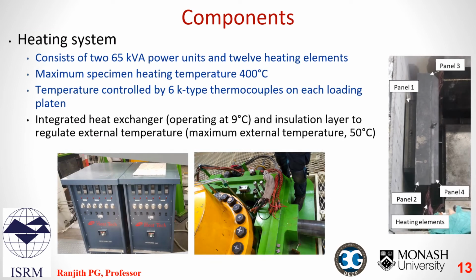The high power heating system is another unique component of this setup. We have connected each loading reaction plate to two heating elements, and the temperature is controlled with a thermocouple connected to each platen. The figure on the right shows the heating element and the thermocouple connections of the top loading platen. The heating elements in the setup are capable of increasing the temperature in the reaction chamber to 400 degrees C.